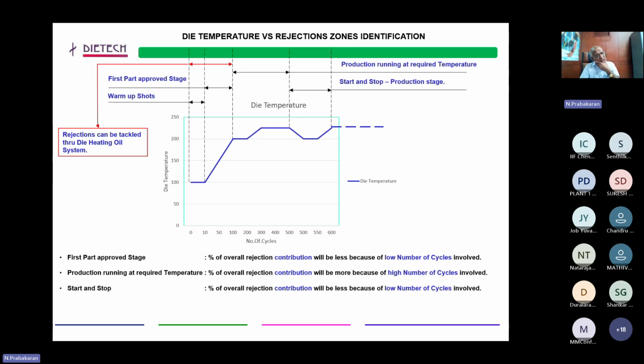Overall rejections, probably 10, okay. 10 is also rejections if you consider it. That is the warm-up shots. The first part approval stage will be around 50 cycles. So altogether, if a shift is producing nearly 400 or 500, it will come to around 10% of the castings. We don't have any answer for the warm-up shots and first part approval in this die chiller and oil chiller.